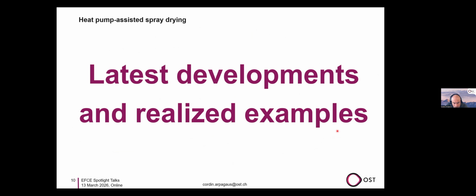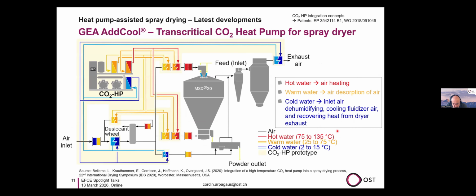So what are the latest developments and realized examples? Here we have the company GEA with their AddCool technology. This is a transcritical CO2 heat pump for spray dryers. The heat pump is illustrated here with 2 gas coolers. They are then heating a secondary loop of hot water. The hot water goes into the air inlet line of the spray dryer and heats up the air up to about 120, 130 degrees.